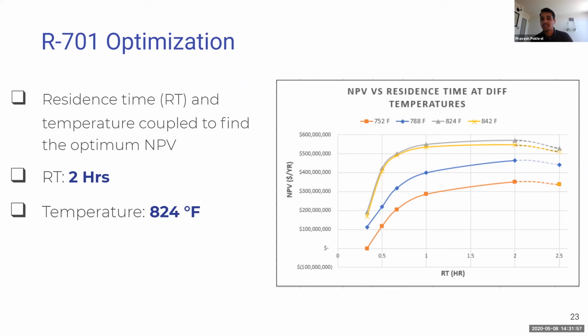Although we validated our kinetics for up to 2 hours, we didn't see any dip in our graph. So we went ahead and did the calculation for 2.5 hours residence time, where we actually saw NPV going down, keeping our optimal point at 824 degrees Fahrenheit and 2 hours.